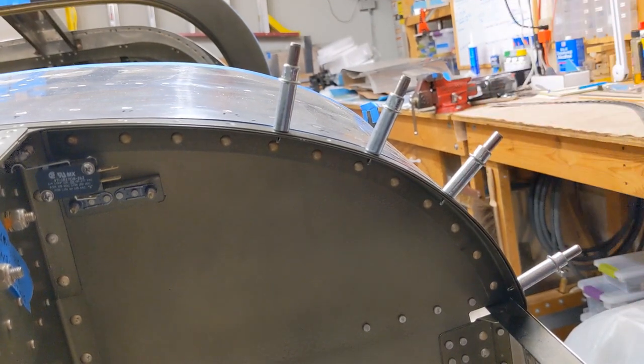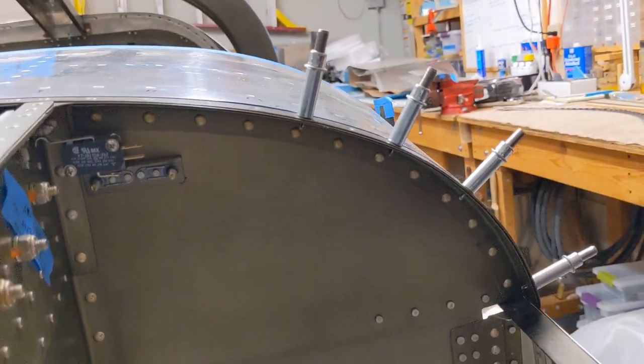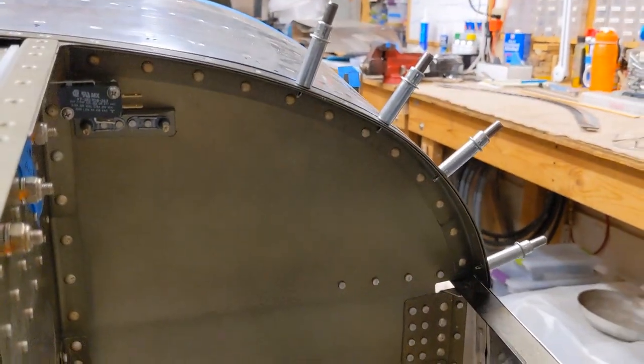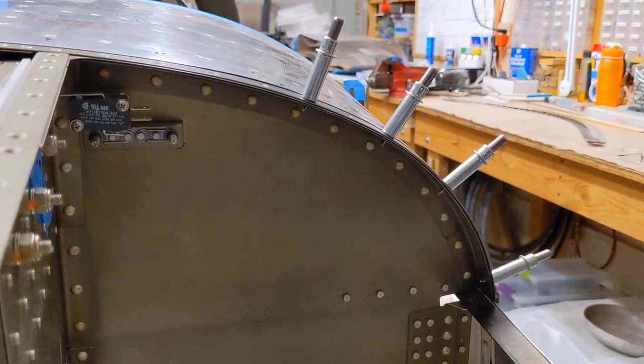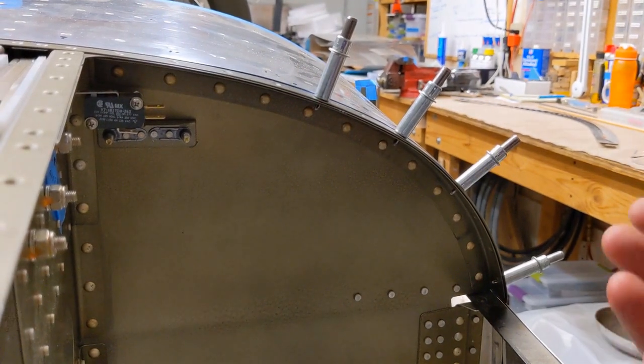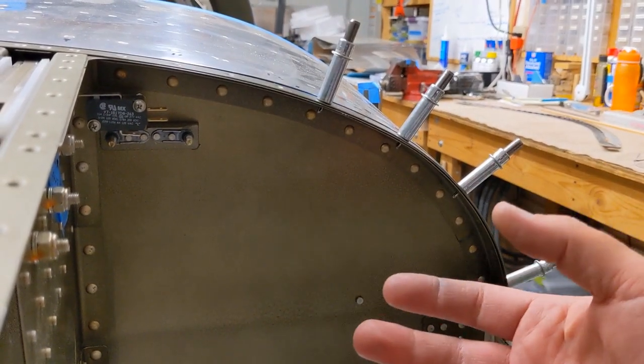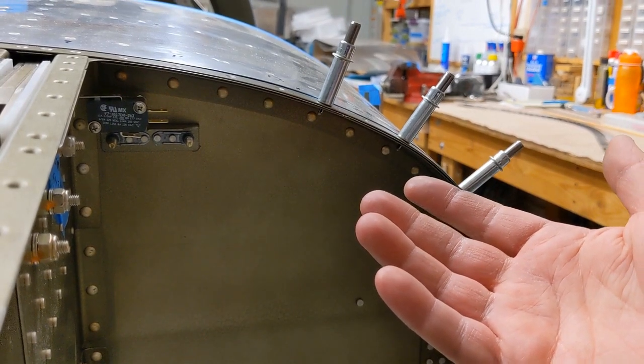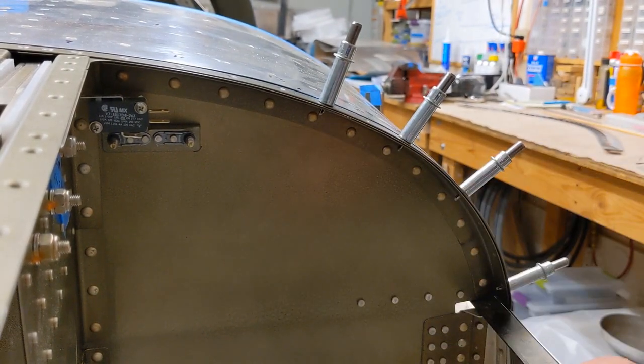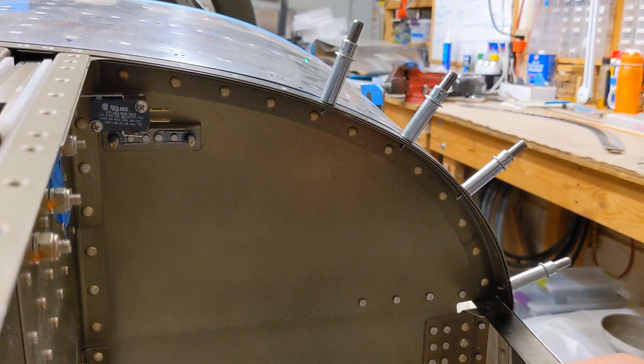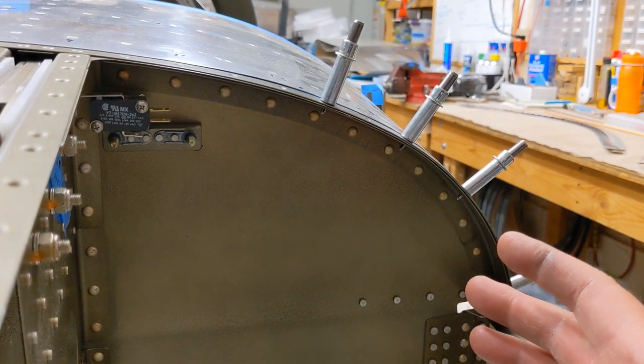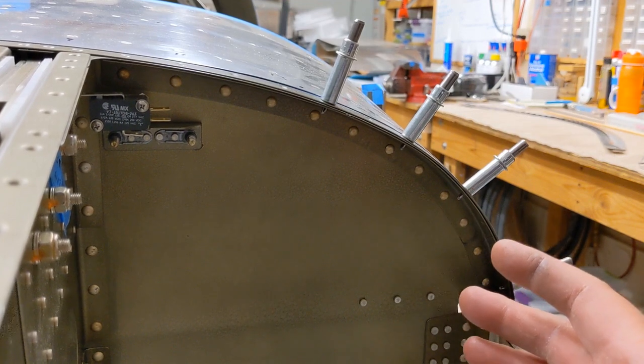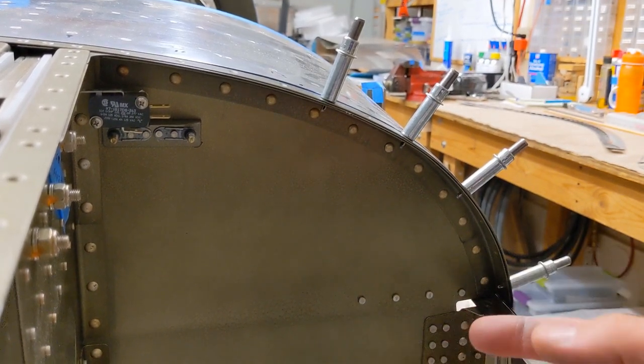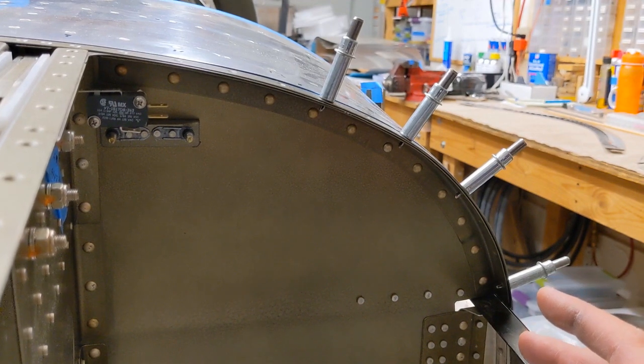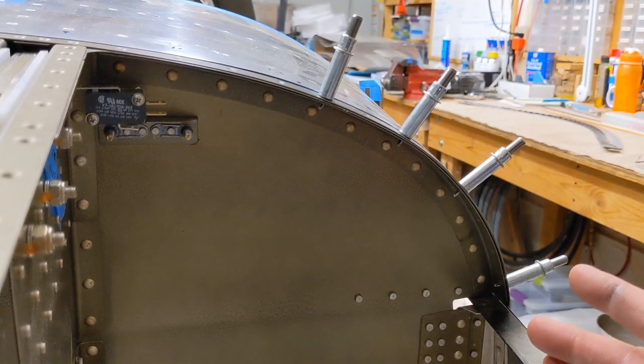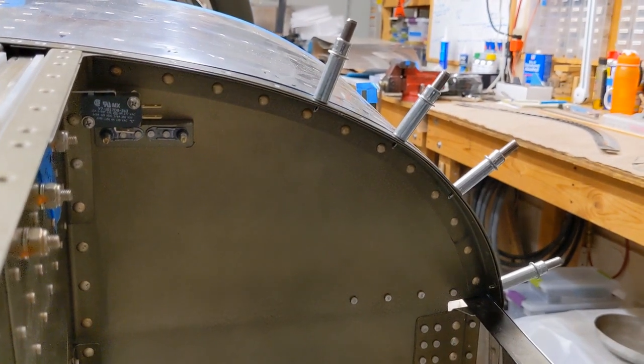And then there's also another piece of knowledge that I have from doing work in the engineering field, which is 2024. When you solution heat treat it, you bring it up to an elevated temperature, and you pull it out of the oven very quickly, quench it in water, and for about an hour, it's in a transient state called W. So you end up with 2024-W immediately after quench. And that W is a transient state. Over the next 4 days, it'll harden up to the T4 condition.